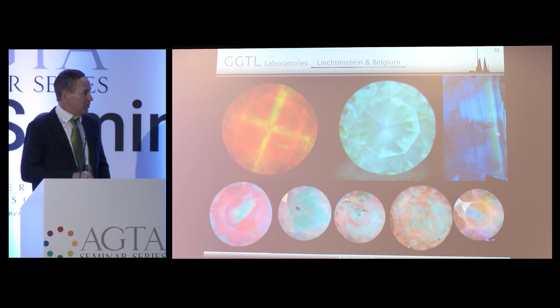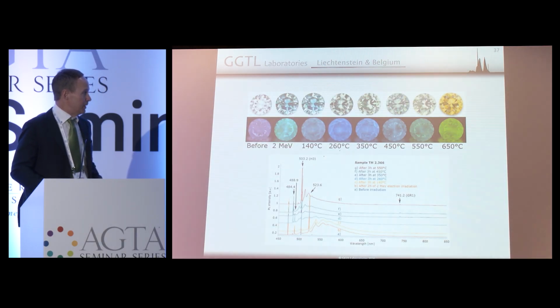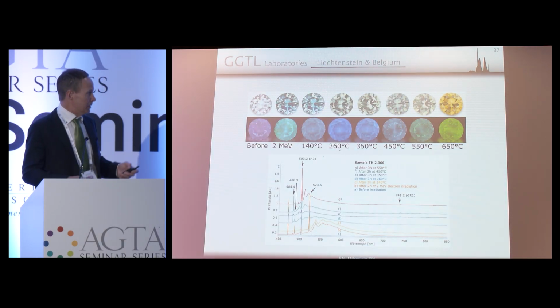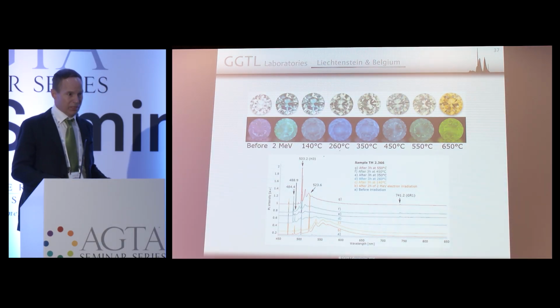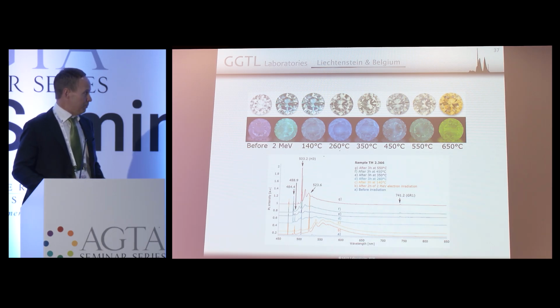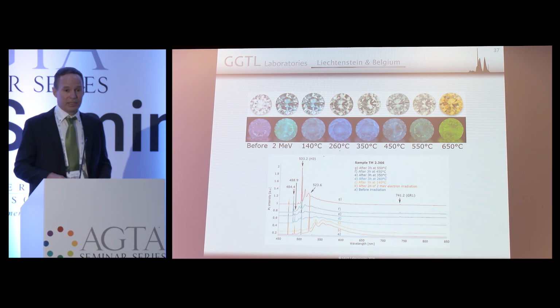So this stone in immersion actually showed just a nice blue color layer right here. Okay, so that gives you a good idea about treatment. To show you what treatment does to a stone, classical stone, and its fluorescence, there you go, colorless type 1A diamond. After irradiation, it went greenish blue, and then we started heating. And you can tell that the color and the fluorescence changes at each step. And at about 650 degrees, it gets dramatic.